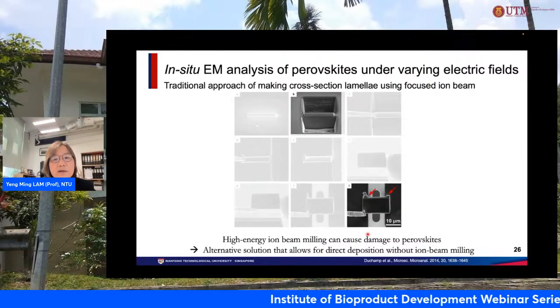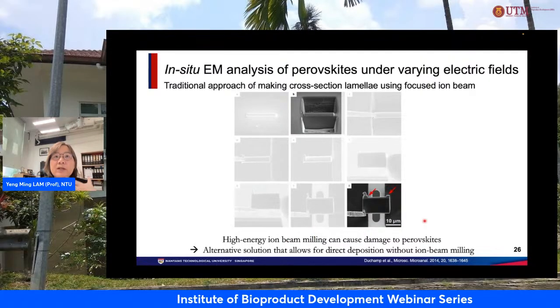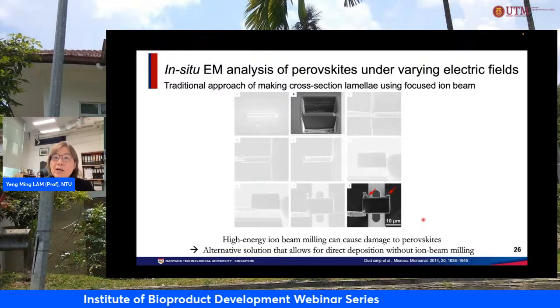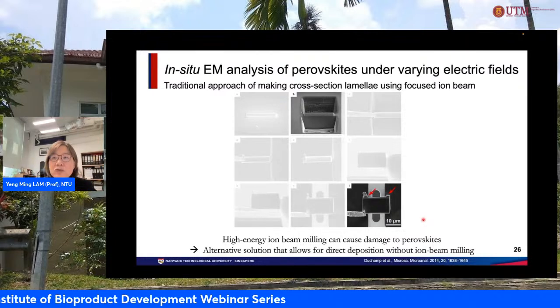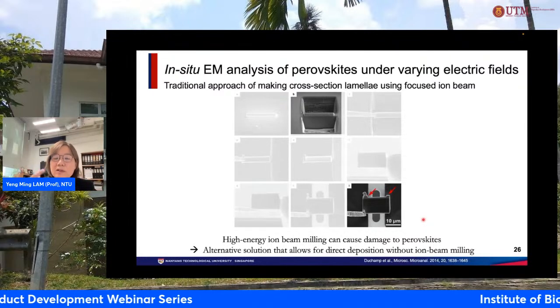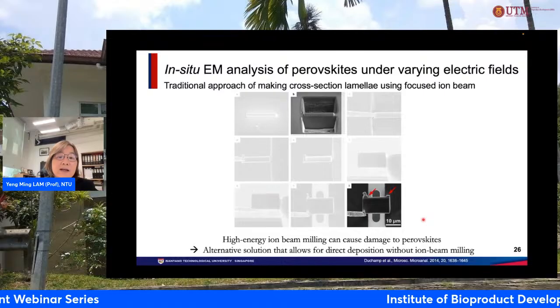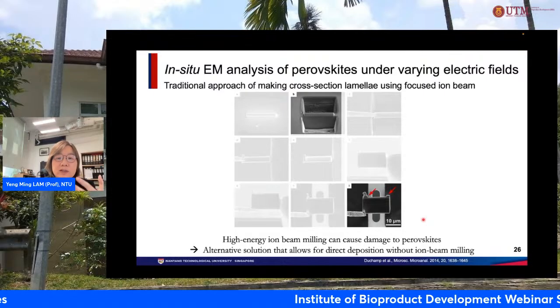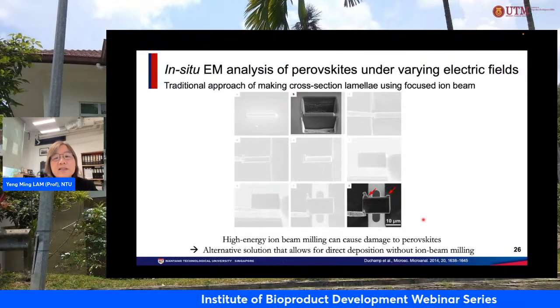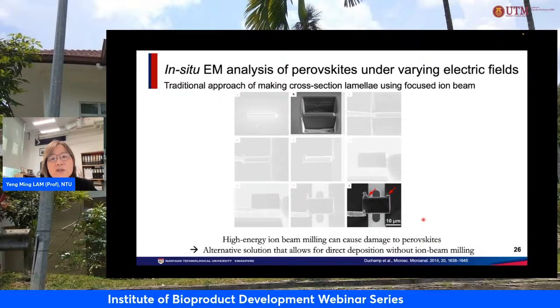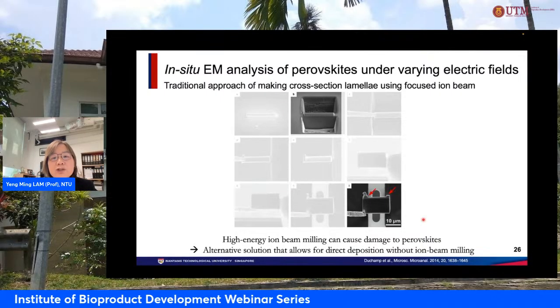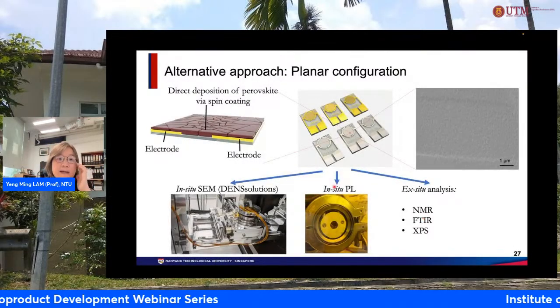So with this kind of high energy ion beam milling, it can cause a lot of damage to this material. So we need to look at an alternative way, because we don't want to impart damage to the material even before we study. A lot of the time, you do not know what kind of damage you will have imparted to these materials before the studies. So what we want to do is to avoid this totally.